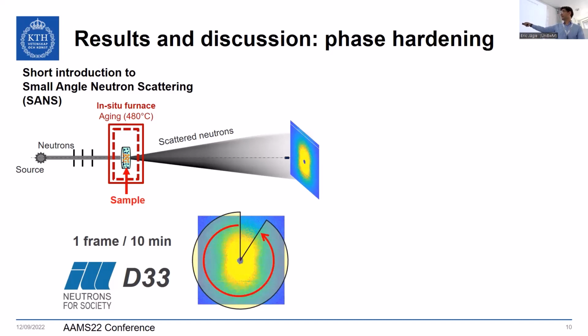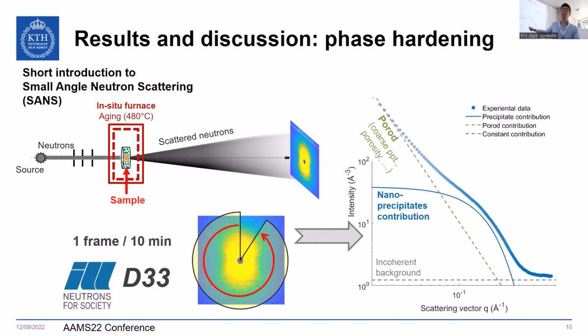With this pattern, we do azimuthal integration, and then we get a 1D curve. The experimental intensities are the blue dots. The dots on the left side are the intensity close to the center of the detector, while the dots on the right are the intensity on the edge. And here you see that we have different contributions on this curve, different scattering. The so-called Porod scattering, which in this case will be caused by coarse precipitates or porosity or whatever in your materials, is this green line here. We have an incoherent background, which is a constant contribution.